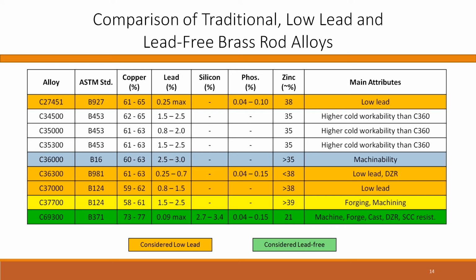The cold working alloys, you can see in the white rows, 345, 350, and 353, have higher copper contents than 360 typically, lower lead, so the combination of the two gives you better ductility, with the main attribute being higher cold workability than 360. So if you've got to bend it or thread roll very, very coarse threads for some reason, for pipe threads, for example, those are the types of alloys they want.